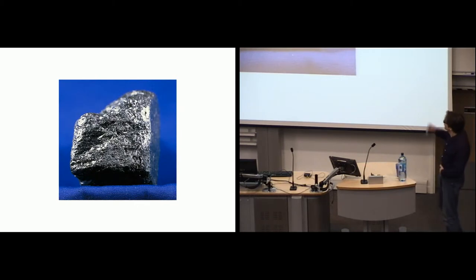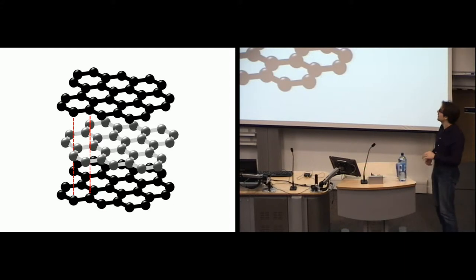That's a piece of graphite. And if we took high quality graphite and zoomed very close, we would see layers of carbon atoms arranged in hexagons within planes. And the distance between planes is much bigger than the distance between two carbon atoms within the plane.